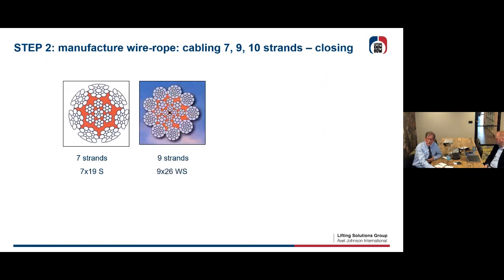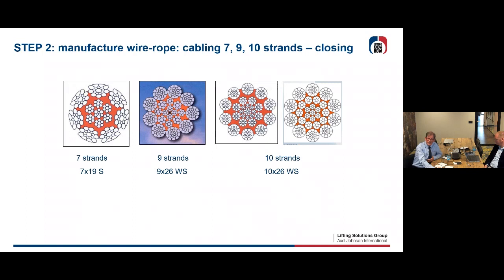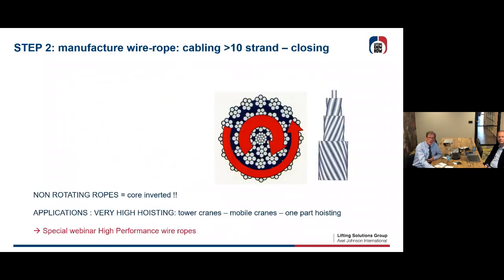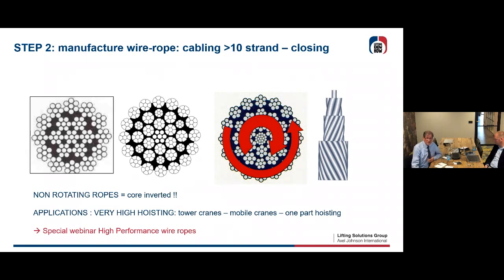Rope. To show that we are not finished at 8 strands, you can have 7 strands, 9 strands, and even 10 strands outside, which makes a rounder rope, more flexible rope, stronger rope. If you have 11 strands or more on the outside, then we normally speak about a non-rotating rope, and be careful because normally then the inner rope is the core inverted, and that's what we call the non-rotating or rotation resistant rope. We're going to talk about this kind of ropes in a special high performance wire rope seminar. It has typical applications for tower cranes, so high lifts, mobile cranes, and one part hoisting.